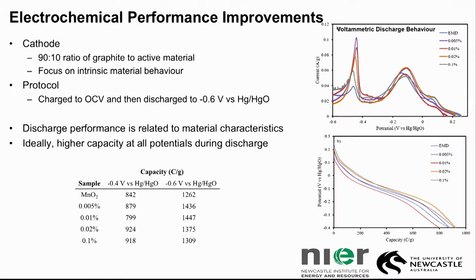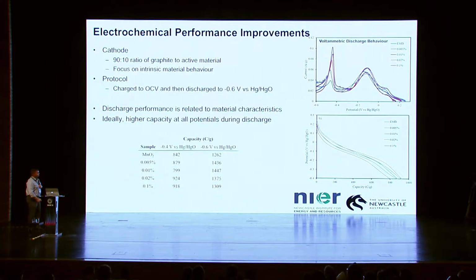That's about a 10% improvement in capacity compared to the unmodified material there. And that's significant. Even though the alkaline system has been around for a long time, there's still a lot of scope for performance improvements here, particularly under high rate applications. And so that's some of the characteristics we're trying to target.